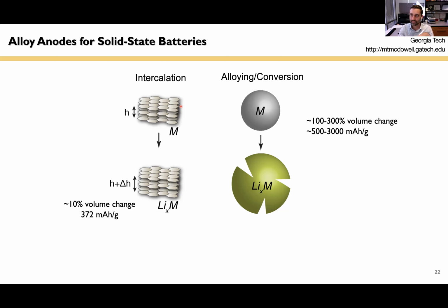But there are other options, and they have particular reasons why you might want to use them. One option is these alloy anodes. So alloy materials are, as it sounds like, materials that alloy with lithium atoms. Examples are silicon and tin and antimony. They're actually quite interesting because not only do they alloy with lithium, they alloy with a lot of lithium. So for instance, silicon will expand in volume by about 300% during incorporation of four lithium atoms per silicon atom. So this corresponds to very high theoretical specific capacities. And in many cases, they could give you overall energy density performance that's quite similar to lithium metal, depending on your battery geometry.